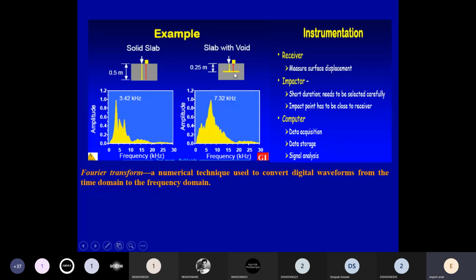Take an example, if there is some kind of void, delamination, or separation in your concrete block or foundation, which is a light concrete block only. Once you give an impact, if there are some voids or major honeycombing, it will go and come back. So your travel time will be less. Once your travel time is less, your frequency will be more. If your travel time is less than expected, why am I saying expected? Because you know this distance is 0.5 meter in this direction. When it comes back, it is again 0.5 meter. So this total distance is 1 meter. 1 meter divided by your velocity, which we have found on some different member of the same grade, we can calculate our expected transit time. If it is less, it indicates either there is a delamination or there is a problem with the thickness.